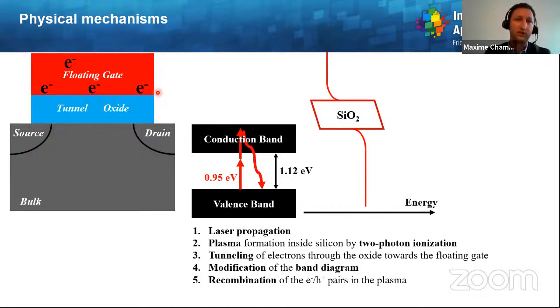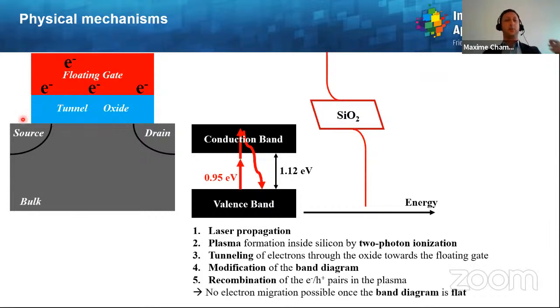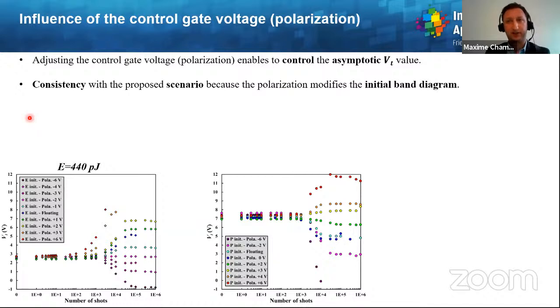and in the end you have more electrons in the floating gate than initially. And by repeating this from one pulse to another, you can clearly see that no electron migration will be possible once the band diagram is completely flat. So in order to test this theoretical scenario, we have carried out 2 experiments.